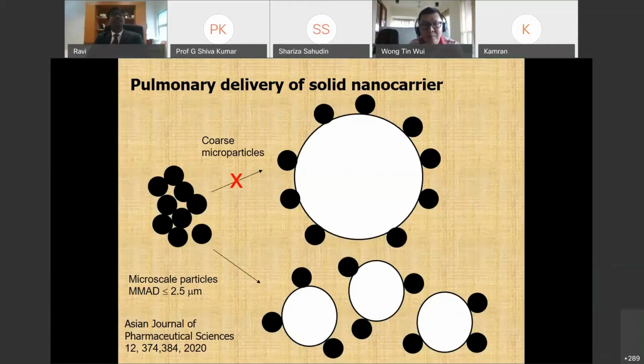Now, if you read through the articles of the past 20 years, the small particles are usually deposited on coarse microparticles. And this coarse particle will then be inhaled in order to deliver the drugs into the deep and peripheral lung. Note that the coarse particles have a size of 200 to 300 micron in general. So more often than not, the nanoparticle will not be able to detach from the coarse microparticle. And coarse microparticles, being a few hundred micron in size, will not be able to reach the deep and peripheral lung. They usually settle at the back of the throat. So when this occurs, there will not be any possibility for the nanoparticle to be inhaled into the deep and peripheral lung. As such, we hypothesize that we should deposit our nanoparticles on a micro-scale particle, which is a few micron in size.